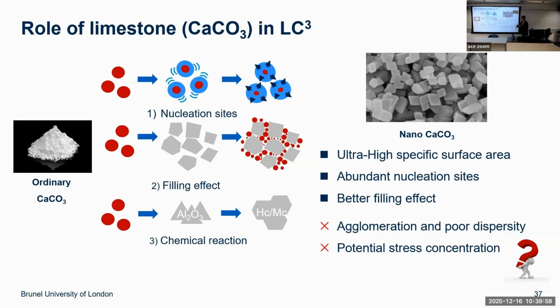But because they're smaller, nano-scale particles always have the problem of agglomeration, which will jeopardize their performance. We're trying to improve their dispersibility so that it can maximize their contribution and unlock their potential. Also, some people find they could hold very minor scale stress concentration, which is not good. But we are not dealing with stress concentration this time.